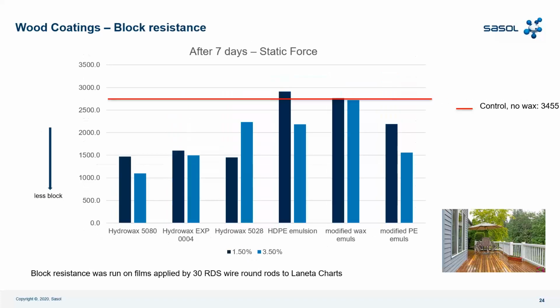Then we have the block resistance. As you know, the block resistance is the union of the static force and the kinetic force. The lower the static force and the kinetic force, the better the block resistance. You need to read this graph with the lower value being better. We have Hydrowax 5080 that achieves at 1.5% the best value on static force, the best value or similar value to Hydrowax 5028, and both achieve a very good performance with respect to the competition like HDPE emulsion or modified wax emulsion or the other modified PE emulsion with a different melting. And this is important to show you because if you need a good block resistance, this graph shows you the performance of our FT emulsion.